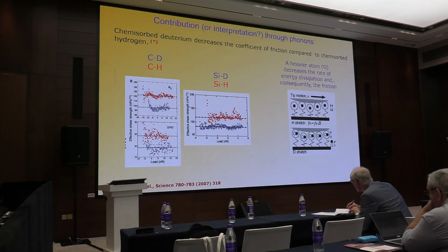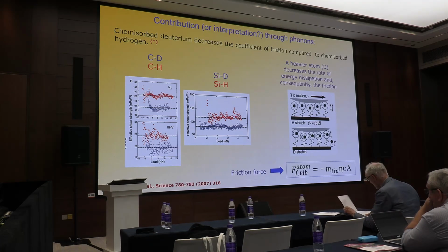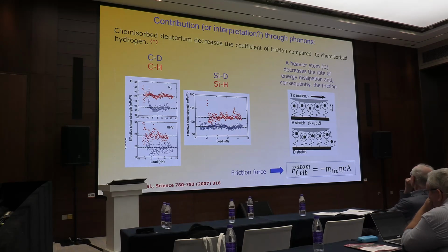Well, a heavier atom decreases the rate of energy dissipation and consequently the friction. This is the understanding and the conclusion of this work. They analyze that the friction force depends on the mass tip. This is the damping coefficient, something like the friction or the shear stress coefficient. This is the velocity or speed, and this is the area, the contact area of the tip. But this is the point here. This is the damping coefficient, the friction or the shear stress, the strength that they measure in their work.